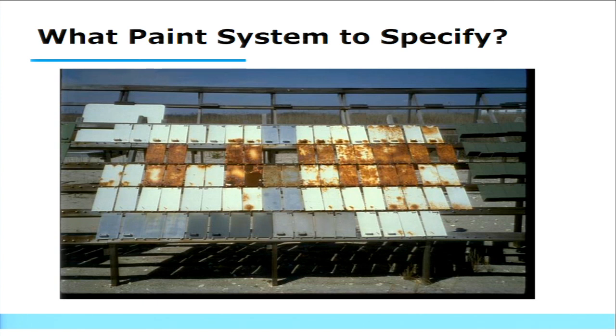So what paint system do we want to specify? As we can see from this picture, there are definitely paint systems that are good and definitely some that are bad. Clearly some in here don't perform well. This is a series of test specimens that the Federal Highway was testing, I believe at Kure Beach is where this is from. And as you can see, some do well and some do poorly. So clearly there are some that we would want to specify in a harsh environment and some that we wouldn't.